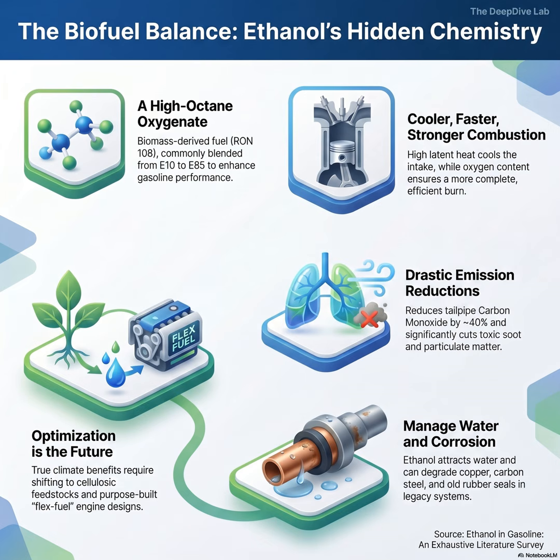The EIS studies revealed that these blends rapidly chew through copper and carbon steel. Ethanol is inherently more conductive than gasoline. Right, because of the molecular structure. And if it oxidizes even slightly, it forms organic acids like acetic acid. It essentially turns the fuel system into a weak battery, acting as an electrolyte that dissolves the carbon steel. Does anything survive? Stainless steel generally survives, but the cheaper metals used in older vehicles are destroyed.